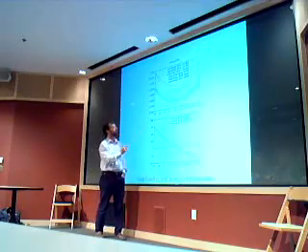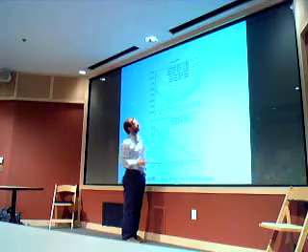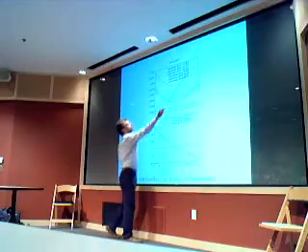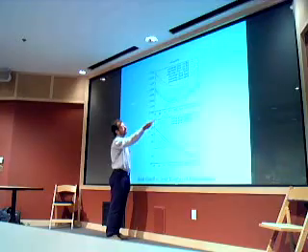So you are making a better job for small lattice parameters and a worse job for larger lattice parameters. And this is why the minimum that you find at fixed number of plane waves is always an underestimation of what you would obtain by interpolating the calculation at fixed cutoff.